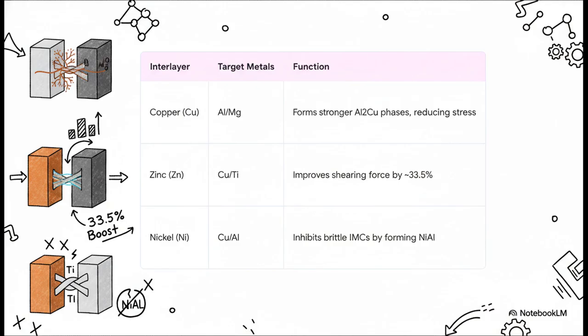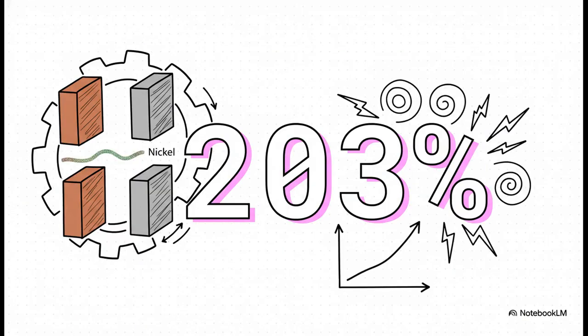A little layer of copper helps aluminum and magnesium form much stronger bonds. A bit of zinc between copper and titanium can boost the joint's strength by over 30%. But nickel, nickel is the real MVP here. You stick it between copper and aluminum, and it acts like a bouncer at a club, actively stopping the most brittle compounds from ever even forming. It's brilliant. So you might be asking, just how big of a difference can this little diplomat make?